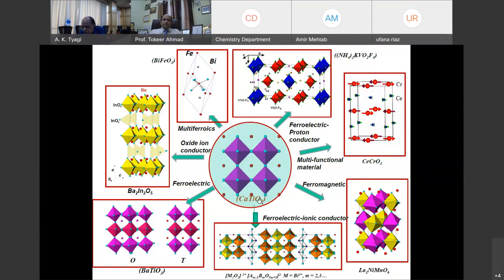Play with the composition, create oxygen vacancy, and beyond certain oxygen vacancies, the vacancies undergo ordering and perovskite becomes brownmillerite, Ba2In2O5, a wonderful oxide ion conductor used in SOFC applications. Replace calcium by bismuth, a lone pair ion, titanium by iron, a magnetic ion, you get BiFeO3, a wonderful multiferroic material. And you can also make oxyfluorides as you see here. You can replace Ca and Ti by two magnetic ions. I will show some results. You get CeCrO3, you can cause ordering of B site. This was the ordering of anion. This is the ordering of cations at B site. You get double perovskite, which are excellent ferromagnetic materials.